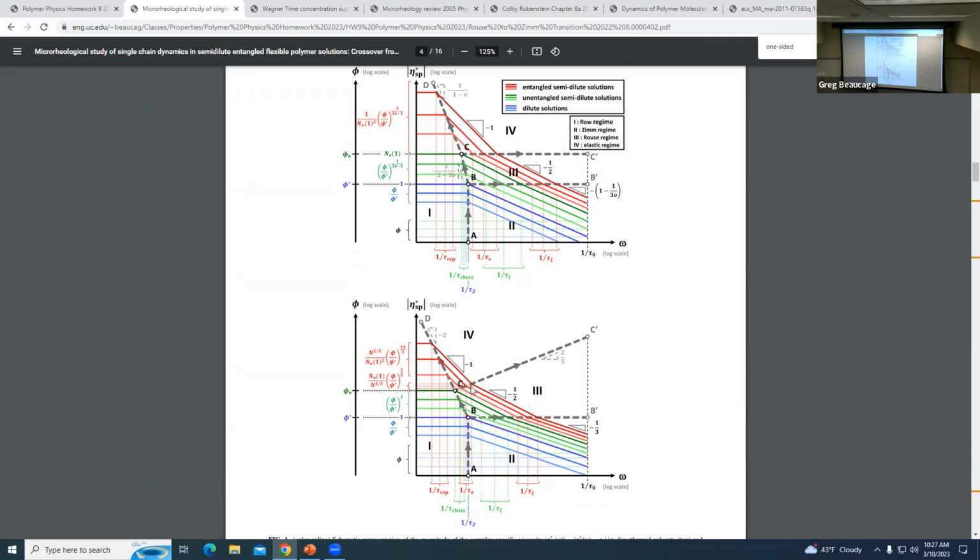And then if it's Zimm behavior, so if you go to higher concentration, then you get entanglements. So the overlap concentration here, the entanglement concentration is a different number. And this is something that more or less was invented by like Colby and Rubinstein, that you have a different number between where the chains overlap and where they start to entangle with each other. So there's this gap. Okay, and they've made a lot out of this gap. So before this, I guess, was mentioned, basically it wasn't made into an industry, so they kind of made this. Colby and Rubinstein kind of made this gap into an industry.